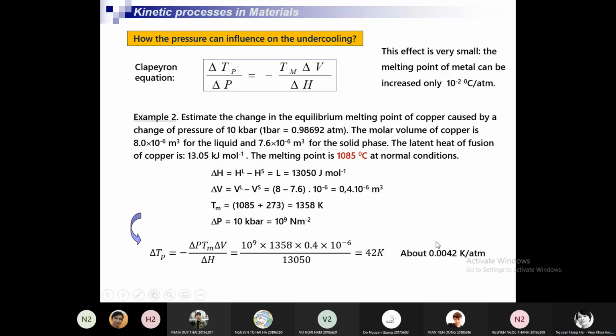It means about 0.0042 degree per atmosphere. Very small value, very small effect of pressure. If you increase one atmosphere of pressure, the melting temperature changes a very small value. But here we have 10 kilobar, which means 10,000 atmosphere, not one atmosphere, because kilobar is approximately equal to a thousand atmospheres.